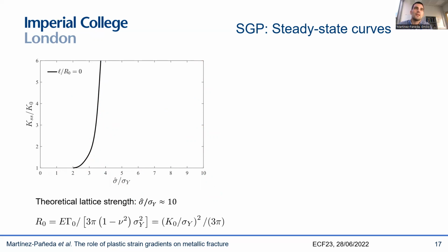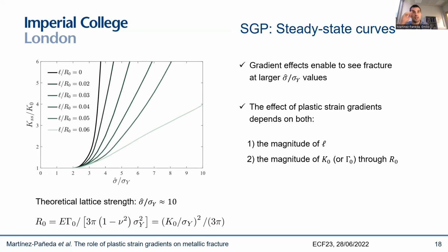However, as we introduce gradient effects into our model, you can see that eventually, depending on the value of this ratio, the length scale divided by R0, we're able to predict fracture even for values of our interface strength that are on the order of 10 times the yield stress, or even for the theoretical lattice strength. So that's quite interesting because, as I said before, this provides a mechanistic rationale to understand why we're seeing cleavage fracture in the presence of plasticity.